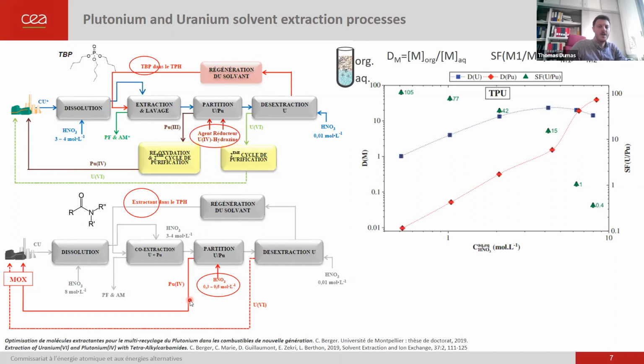How does this work? Okay, we can use this sketch to understand, and then I will go to spectroscopy to explain why what we do is useful to understand that. You can measure a distribution ratio. It's the ratio between organic concentration and aqueous concentration of a metal over the acidity of the aqueous phase. And you see that the more you have an acidic solution, the more you are going to extract plutonium, for instance. Here, that's the red points. And you also can measure the separation factor between uranium and plutonium just by doing the ratio of the distribution ratio. That's the green points that are here.